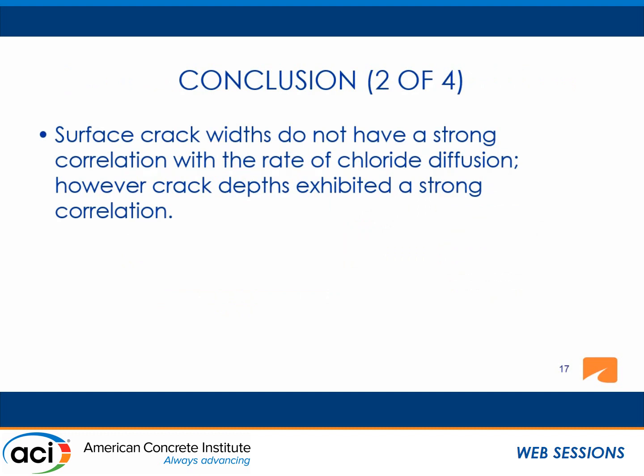We have the surface crack widths. We found no significant correlation, while the crack depth seemed to have much better correlation with the chloride diffusion.